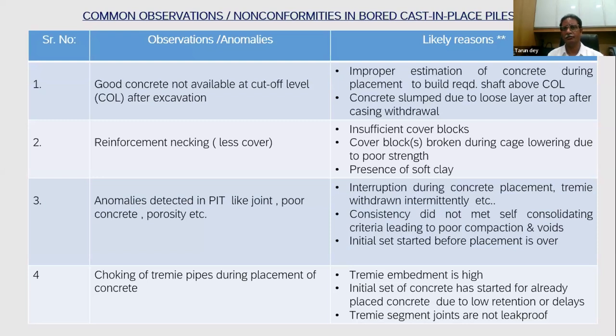Ideally, the mix of the cover block should be similar to the concrete of the pile. Presence of soft clay, which is not in your control, could be a probable reason for the necking. Anomalies detected in PIT, like joint, poor concrete, porosities.